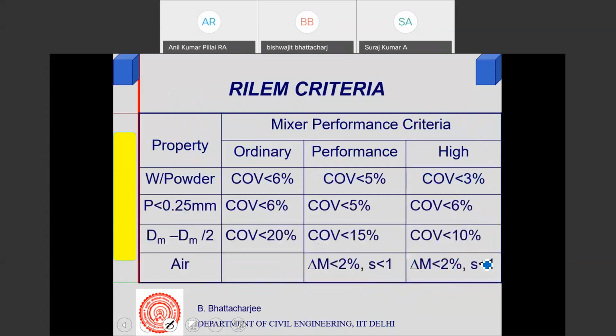And there are criteria from RILEM. It says that, basically, the coefficient of variation, which is standard deviation divided by mean, or S divided by X bar. You have done several tests, find out their mean slump, let us say, and the standard deviation of the slump from 5-6 tests. And if this ratio is less than 6%, it is ordinary. Above 6% is not acceptable, I mean, it will not be good enough. So this water to powder ratio should be less than 6%. If it is less than 3%, the variations are less, then you call it excellent. So that's the RILEM criteria.